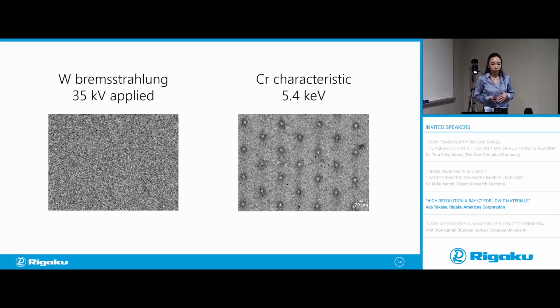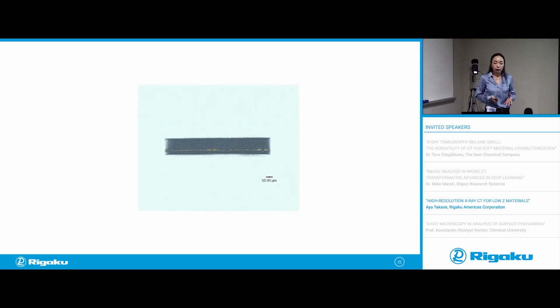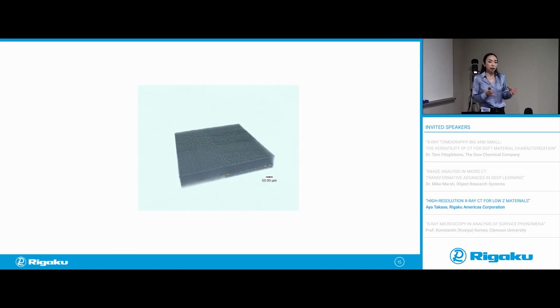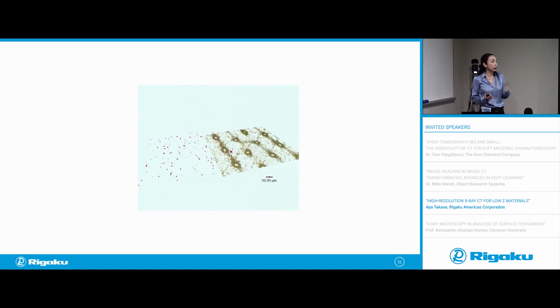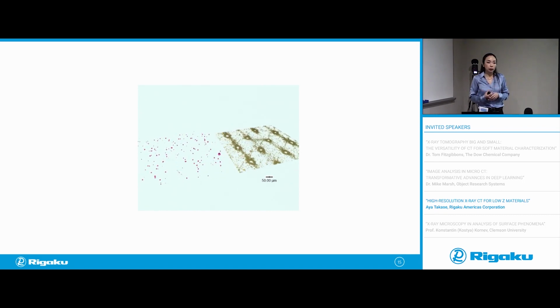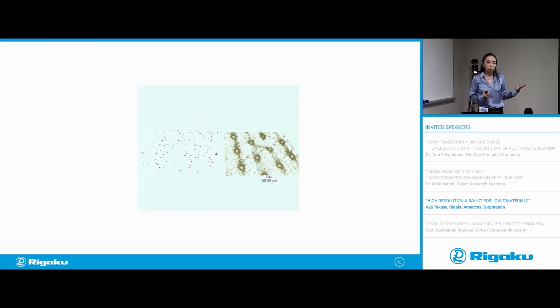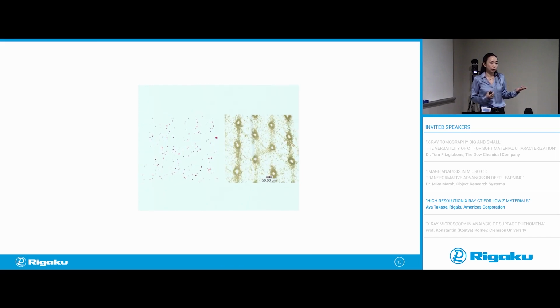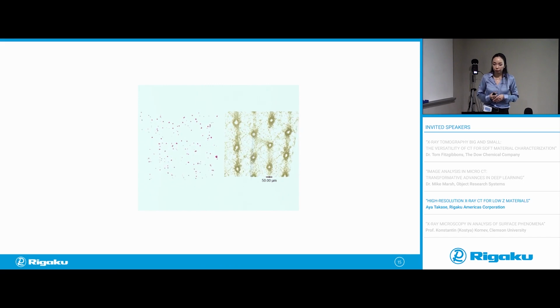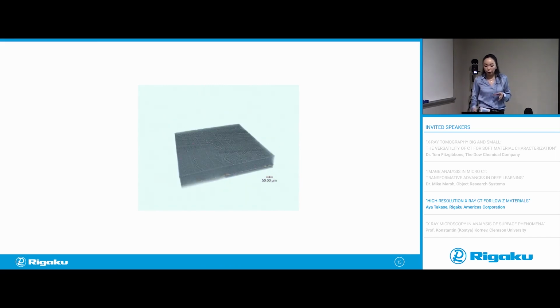membrane filter. And this is just a 2D projection, but you can do a full CT scan and see an image like this. And because you are creating enough contrast between the sandwiching organic films and the 3 micron thick membrane filter, you can segment them, and you can see some fillers as well. And this can be done by using low energy X-rays, in this case 5.4 keV. So this is about the contrast.